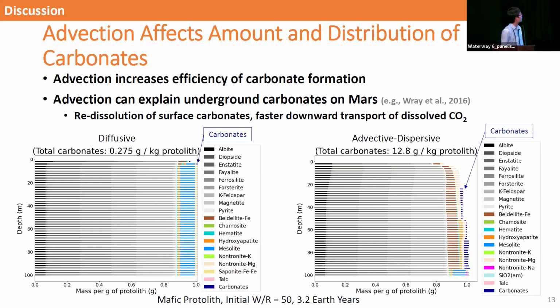And next, we look at the effects of advection on carbonate formation. So by comparing different simulation cases with diffusive transport and advective dispersive transport, while other variables are kept constant, we can see that advection greatly increases the efficiency of carbonate production, with the advective dispersive case shown on this slide producing 2 orders of magnitude more carbonates than the diffusive only case. And we also found that advection can cause the production of underground carbonates by causing redissolution of surface carbonates and also accelerating the downward transport of dissolved carbon dioxide to precipitate carbonates deeper down in the crust.